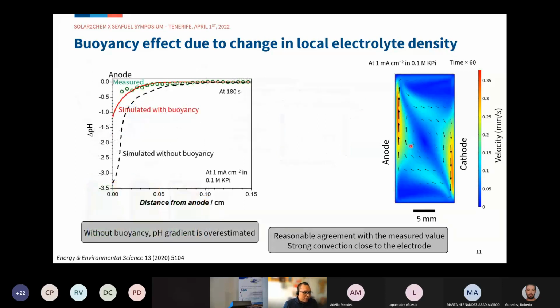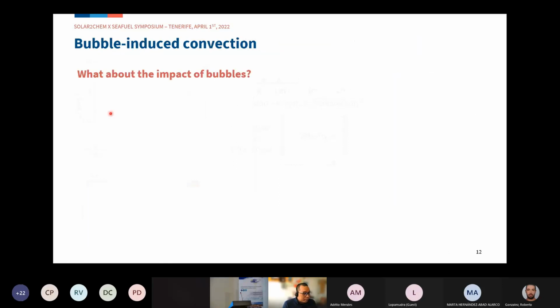The importance of buoyancy is shown here, where we compare the measured delta pH with the simulation. When we consider no buoyancy effect, the simulation results in this black dashed line, and we significantly overestimate the pH gradient. We can only resolve the experimental data when we introduce the buoyancy effect into our simulation. This suggests we also need to consider this further.